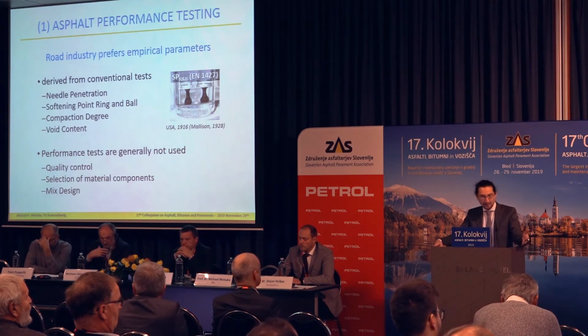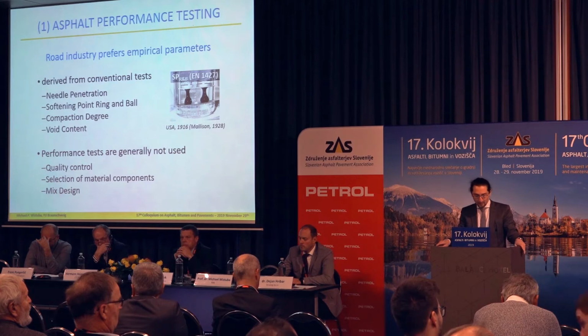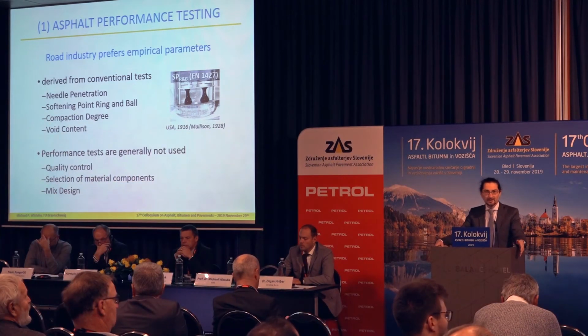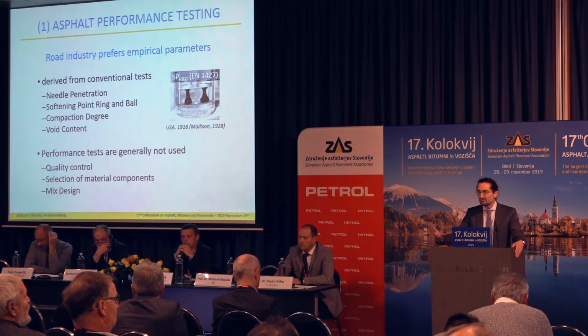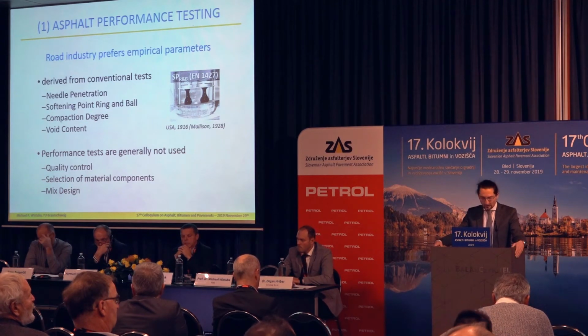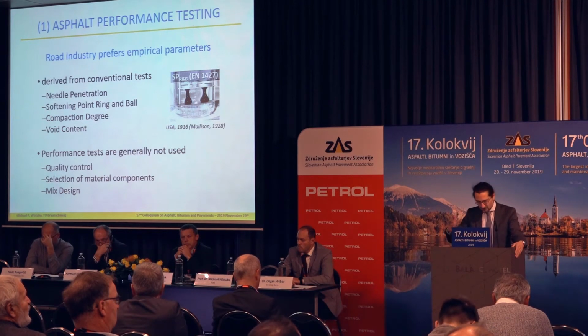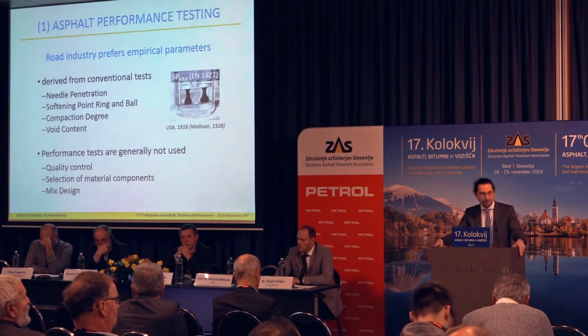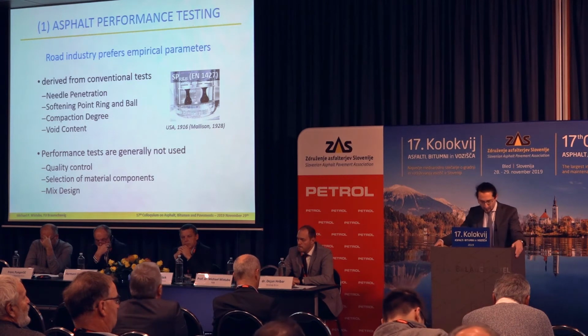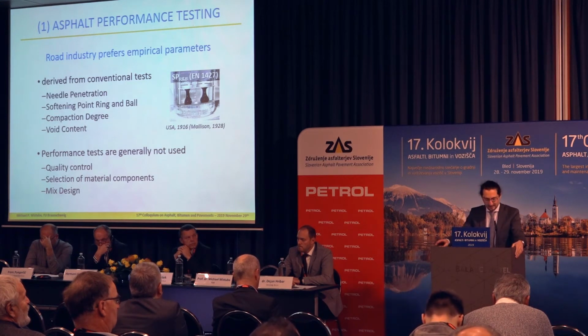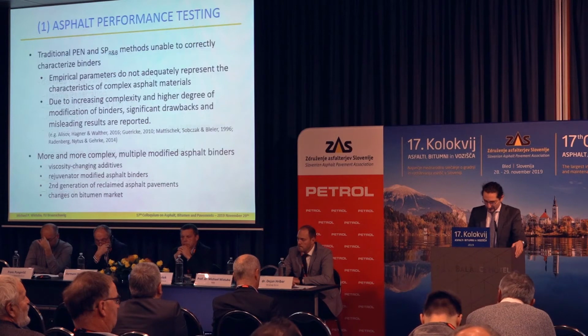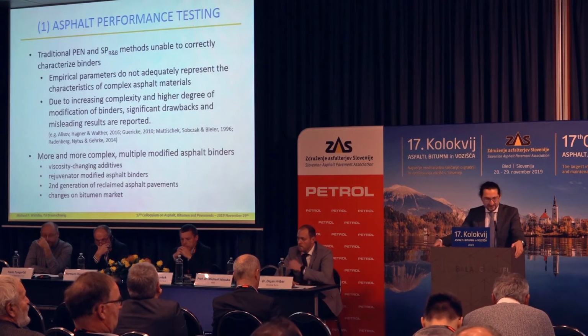They stick to needle penetration, to softening point, ring and ball, to volumetric parameters like compaction degree and void content. No wonder that the idea of performance testing is more or less not used in routine work, not for quality control, not for selection of material components and mix design. It's not appropriate for routine work. So the road industry sticks to traditional parameters.